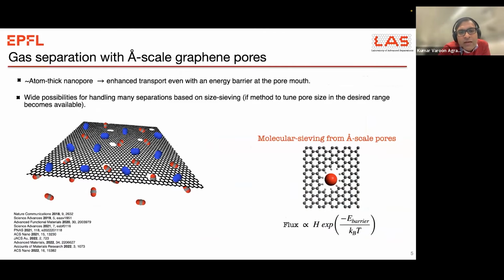One, it is a membrane that has a selective layer thickness of just one atom. And this is essentially motivated by the fact that a thin film would give you the highest possible flux. That is very important because if you have a thin film and a high flux, then you need only a small membrane area, and that would reduce capital cost. So these membranes can be very attractive when you want a small footprint of your process, where footprint is important.